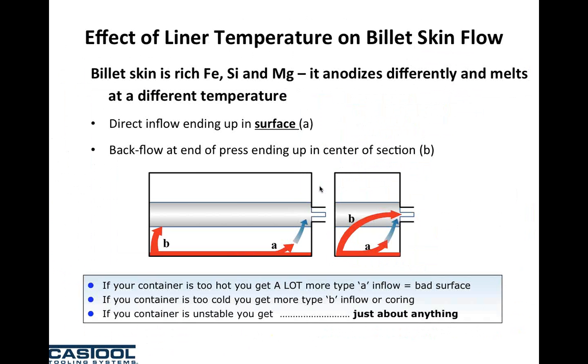Also, the temperature of the liner would affect the billet skin flow. What you want is a consistent temperature differential between billet and your liner surface of around 50 to 60 Fahrenheit. So you can hold back the surface defects and keep them there as a skin, and you can use a cold cleanup block to clean after. If you don't know the temperature of the liner surface, you don't know if the skin defect is going to stay at the shell or go into your profile extrusions. So it could be just anything if you don't control the liner temperature, or if you don't have the thermal stability of your liner. Again, the goal is to keep 100% of the inverse segregation and oxides in the butt. What we don't want to happen is any of that leaking into the profile.